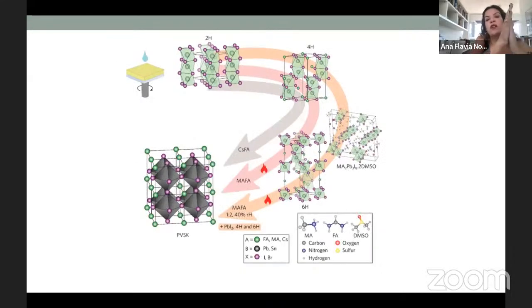From all of these works, we show the mechanism of the formation of these perovskites. Of course, this is very complex and depends on the composition, depends on the humidity or other factors, and if you are annealing or not. But as you can see, we start with the hexagonal phases, and from the hexagonal phases, sometimes you pass through a complex, an intermediate, otherwise you go straight to the cubic perovskite. In some cases, you really need to complete this stage by annealing the film.